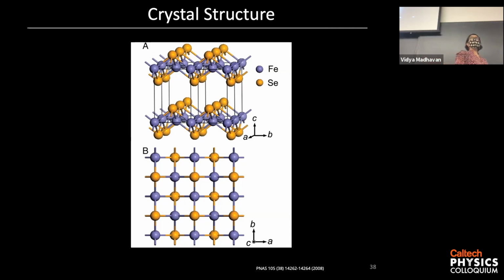So this is the crystal structure of iron, selenium, tellurium. The reason I show you this is that when we prepare surfaces for STM studies, we actually break the surfaces. So we cleave the material. This particular material is really nice. It cleaves right here, and it exposes the tellurium plate. So you can see these yellow balls. Those are the tellurium atoms.